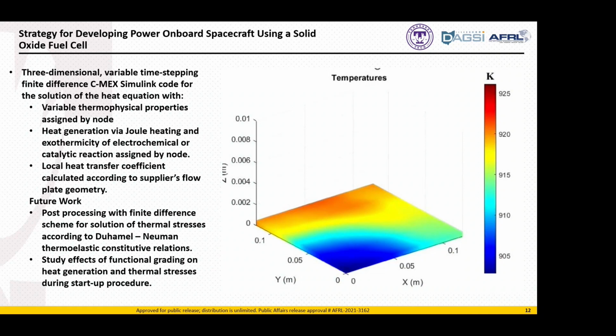So something that we want to manage is if we have a flow which is orthogonal. So most of these fuel cell stacks, the fuel and the oxidizer are actually flown orthogonal to each other, and so the problem can no longer be reduced by some type of symmetry to a one-dimensional or a two-dimensional model. So we've had to develop full three-dimensional models that will run in Simulink. And so I created a three-dimensional variable time-stepping finite difference code in C that we've embedded into Simulink. It solves the heat equation with variable thermophysical properties, so we can look at the electrode, the electrolyte with separate material properties.